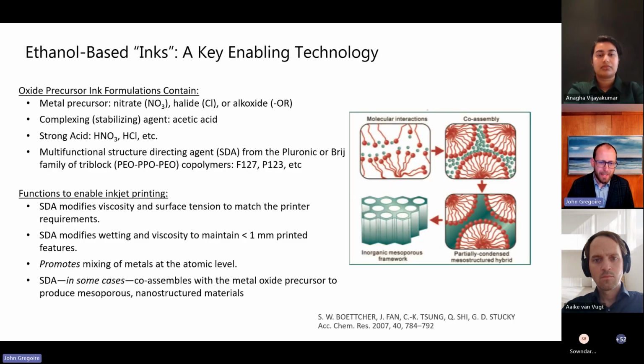Okay, backing up to the origins of this technique, but also it'll come back around in the end about where we think synthesis needs to go in this field. These ethanol-based inks where you can dissolve metal precursors were really pioneered by the Galen Stucky group at Santa Barbara and involve a number of components in this ink. A lot of them promote solubility and stability and match the viscosity and surface tension needs of the printer, but also these structure directing agents that sometimes form micelles where they can organize the metal precursors so that when they get converted into metal oxides via calcination they can form specific nanostructures.